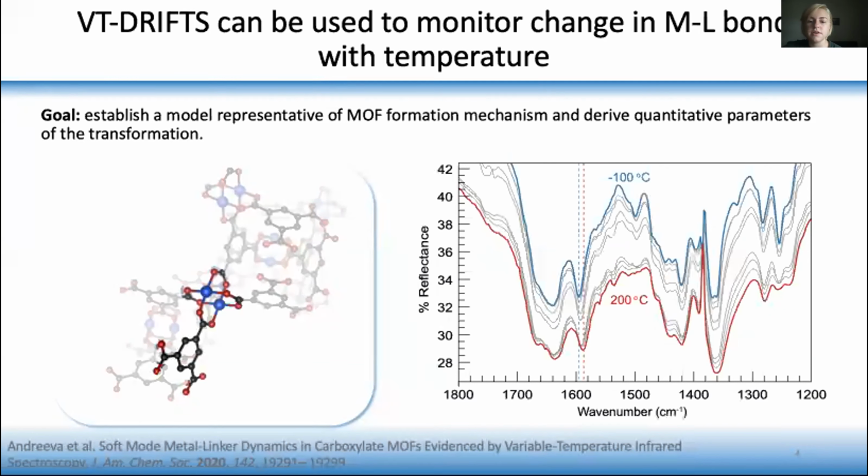And here is the IR spectrum of this material. Upon collecting data, we do see the redshift in the peaks attributed to the CO bond. What we're looking for is the change in energy at which the CO bond appears. And what we expect to see is the lowering in energy of the CO mode with increased temperature, due to phonon losing its energy by coupling with another vibrational mode, that is metal-oxygen.